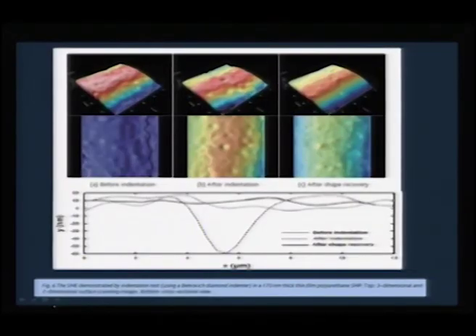help. Here again there is another example of a shape memory effect, where you actually do indentation. In other words, you try to apply very high stress, and in this region you can see a dent is formed. This is before indentation, that means you are applying very high pressure, so it has made a mark, but once you heat it, it recovers the shape. So this is the depth of your indentation. You can actually go minus 60 nanometer, you can just plunge it with a pressure, and then once you heat it back, it again comes back to the same shape. So, the shape memory polymer incidentally can bring back the shape that you are looking for.